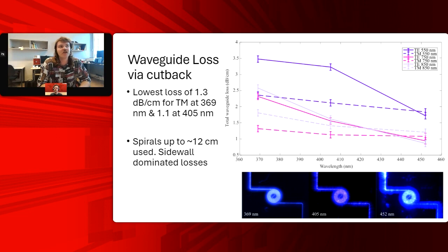We see a reduction there from about 15 dB. Let's say it's at 405 nanometers. Just recently, I was measuring chips at 405 nanometers. We saw 15 dB coupling losses per facet, which is huge. I gave them to Nadia, a coworker heavily involved in the patterning, and she was able to polish them. We brought that down to 5 dB per facet. So polishing can make almost a 20 dB power budget save when it comes to polishing the coupling regions. Mm-hmm. Yeah, extremely important. Very cool.